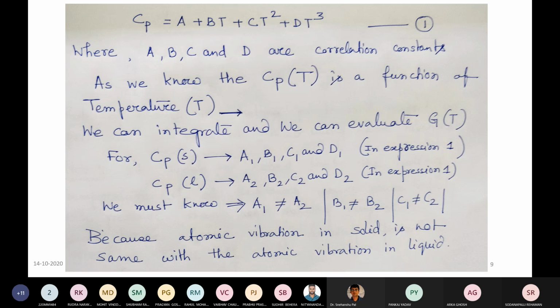Now, for the Cp of solid, the correlation constants are A1, B1, C1, D1 in expression 1. In the same way, for the Cp of liquid they are A2, B2, C2, D2. One must remember that A1 must not equal A2, B1 must not equal B2, C1 must not equal C2, and in the same way D1 must not equal D2. Why is it so? Because atomic vibration in the solid is not the same as atomic vibration in the liquid. And that is the very important part.